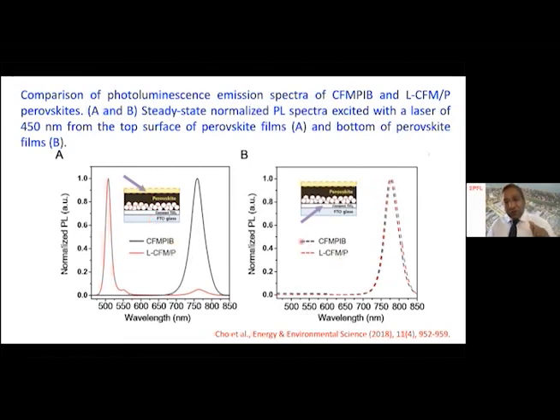Now, if you interrogate from the bottom side, from the FTO glass side, both the samples, the reference sample as well as the layered perovskite sample, show only one emission maximum, showing that the two-dimensional perovskite is limited only to the top side, not penetrating into the bottom side of the electrode. So this demonstrates the exclusive deposition of the two-dimensional perovskite on top of the three-dimensional perovskite.